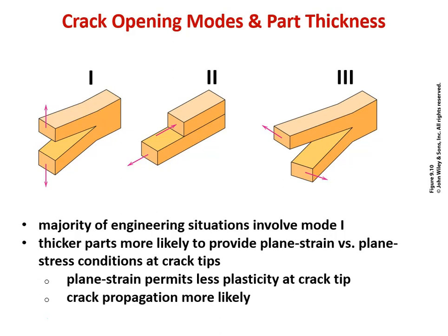Okay. Crack opening modes and part thickness. This is a little bit of vocabulary that's usually used with respect to fracture testing, and it's relatable to the way we use materials in the field. So you can think about if we have a material that has a crack that we're loading, we can either apply a stress that will open the crack, sort of like the mouth of an alligator, which you can see on figure number one. We can put it into a front to back shear state, like you see in schematic number two, or we can apply shear in kind of a tearing mode, like you see in schematic number three. Those are the three orthogonal directions in which we can apply stress to a pre-existing crack in a material.